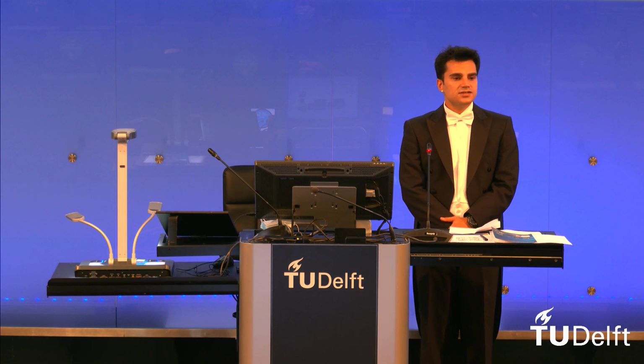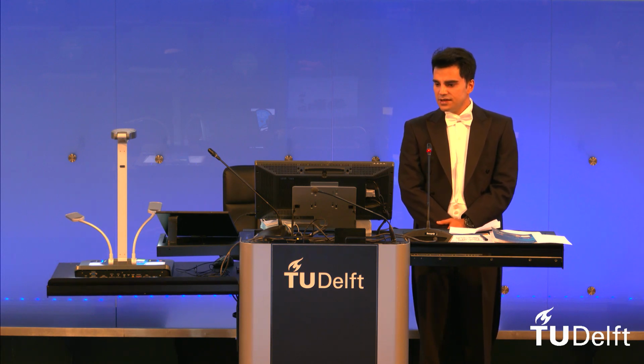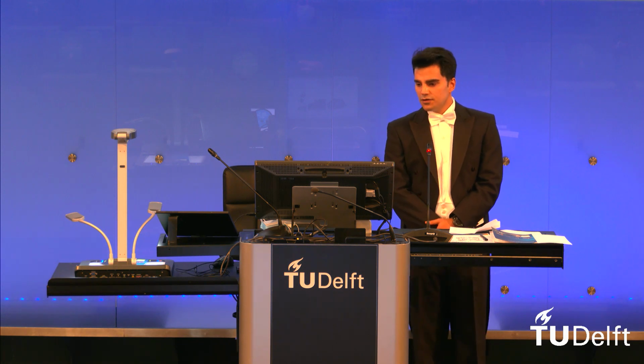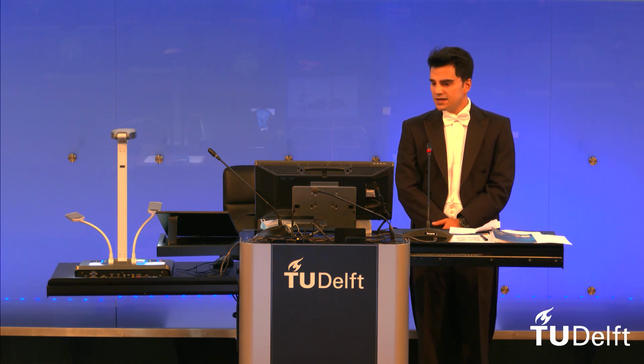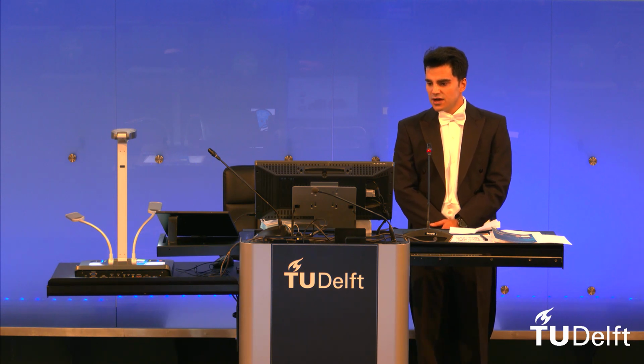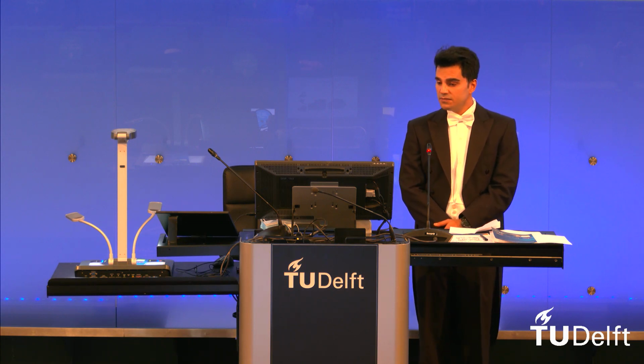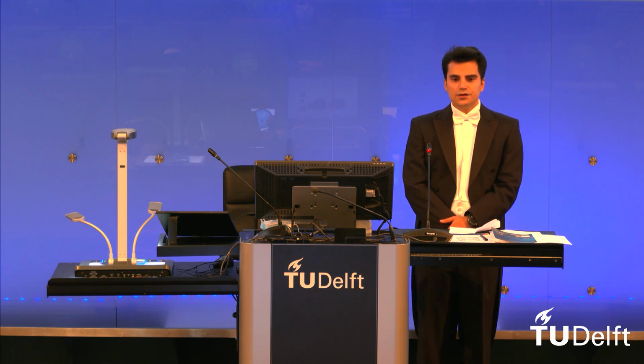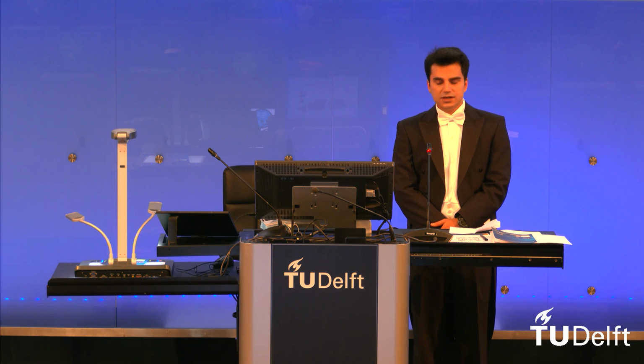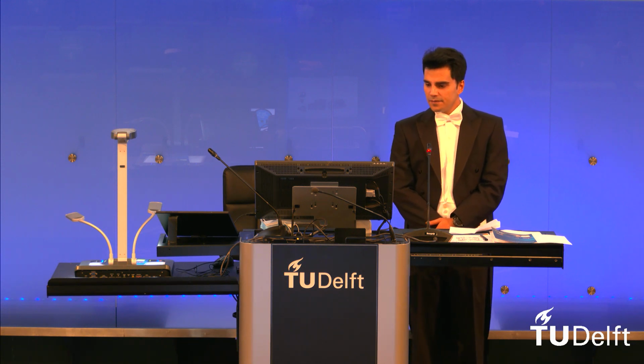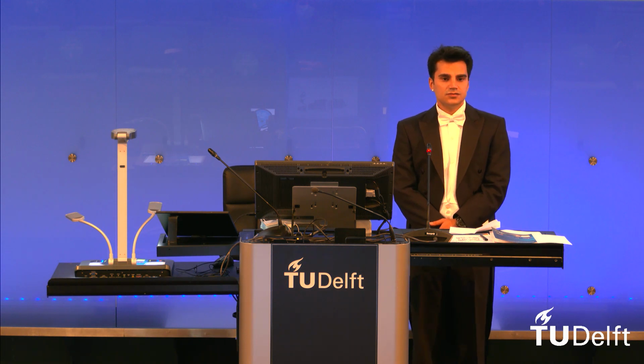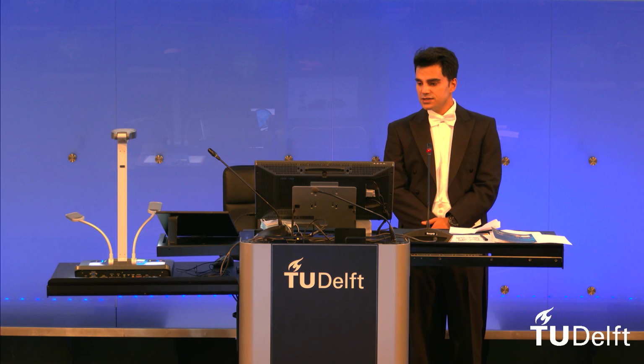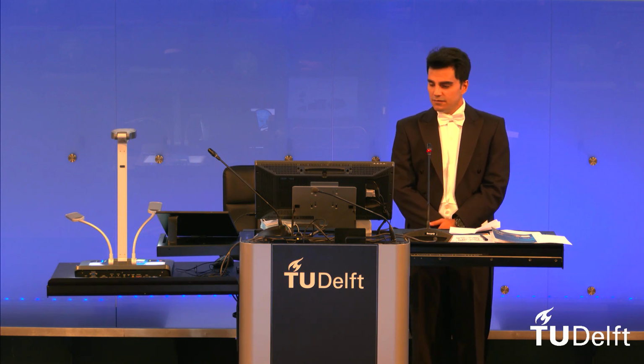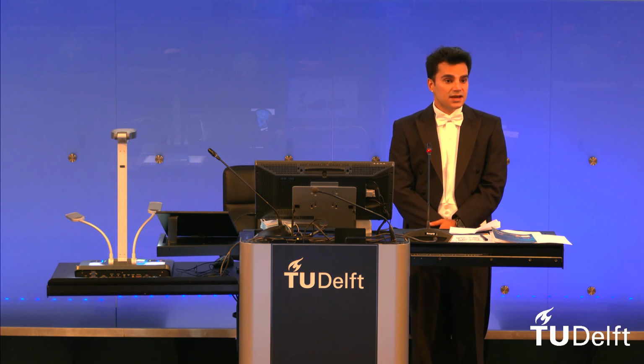The key features of the test rig are nominated here. You see that we have used a proper scalability in order to have a scaled environment in the test phase. The test rig is designed for the overall scale of 1/5, which has the flexibility of having smaller or bigger wheel track elements. The real wheel rail conditions on real wheel rail materials can be included in the test. The main idea of this test rig is to apply and to include the high frequency vibrations generated due to impact loading, which are present in reality. So we want to mimic them also in the test environment.